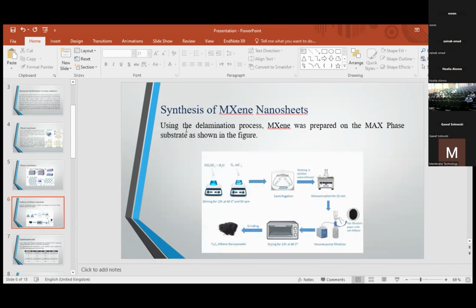For the synthesis of MXene, we are using the delamination process. MXene was prepared from the MAX phase substrate as shown in this figure. The etchant solution was pre-mixed and contained ammonium hydrogen difluoride, NH4HF2. Then the MAX phase powder was gradually added and stirred for 12 hours to remove any potential MAX aggregates. The produced Ti3C2 slurry was centrifuged and then placed in the ultrasonic. Lastly, the final product was filtered with vacuum pump filtration and dried in an oven that was heated to 80 Celsius for 12 hours.